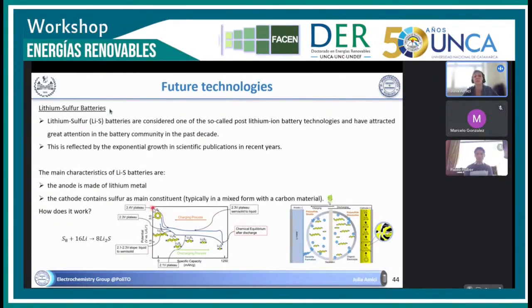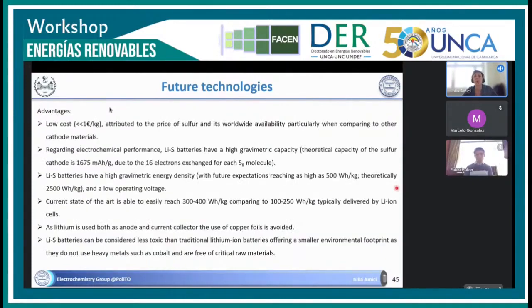Sulfur is present as a ring of 8 sulfur atoms, which gets opened by the lithium ion, and it forms shorter and shorter lithium polysulfide chains. The interesting fact is that for one molecule of sulfur, 16 atoms of lithium react, so you exchange 16 electrons. That's why the specific capacity of the lithium sulfur battery is really high. It should be around 1,675 milliampere hour per gram.